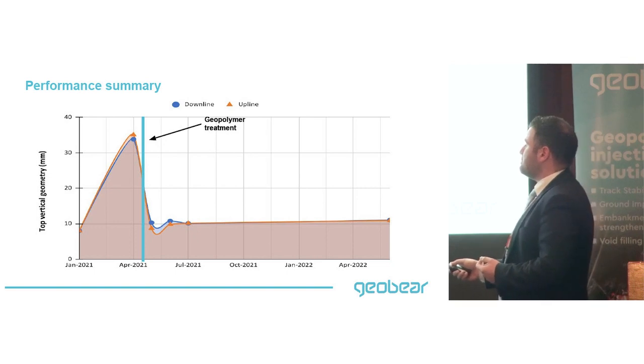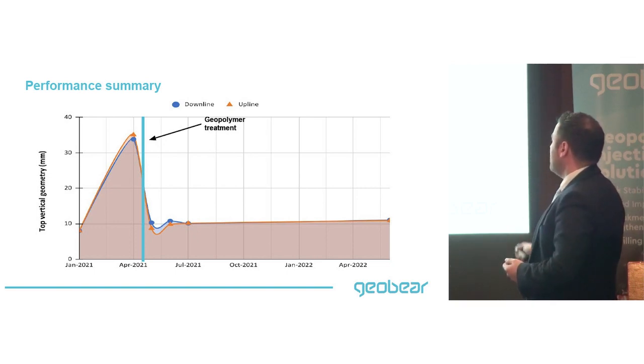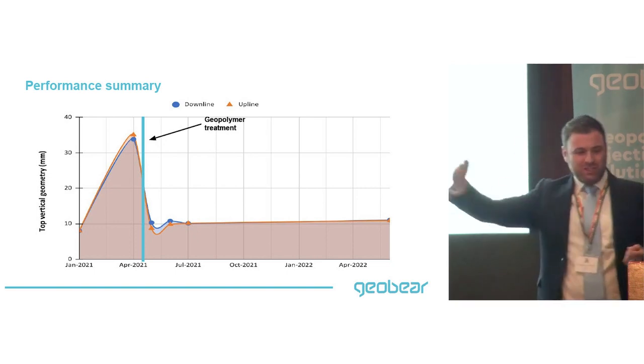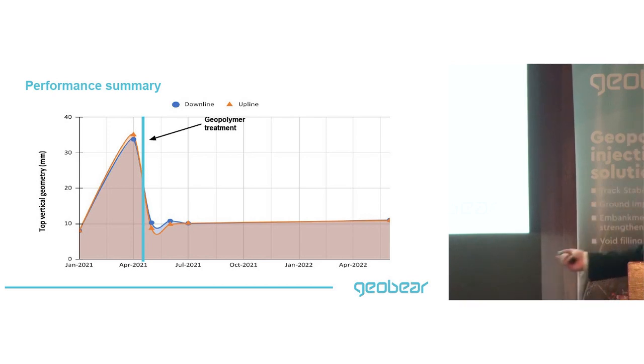So we've taken 3 measurements after the treatment, and then looked at the measurement almost a year after to see what happened. What we've realized is that it seems to have actually stabilized. So we didn't just lift the slab, we've actually managed to stabilize the deterioration.